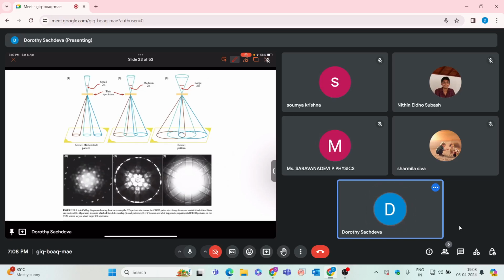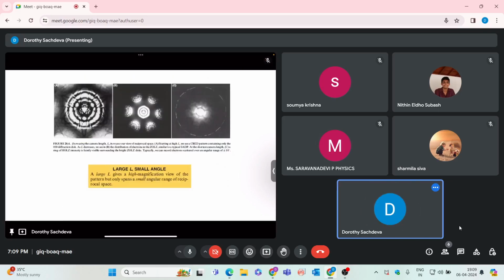So this basically shows how on changing the C2 aperture size, your CBED patterns will change from individual discs to completely overlapping discs, like in this F diagram. When you have a smaller aperture size, you have the individual spots separated. But as you increase the C2 aperture size, your diffracted spots get converged and you get this CBED pattern, and at last you will get this CBED pattern on the TEM screen with this high C2 aperture size. So this is just the same thing.